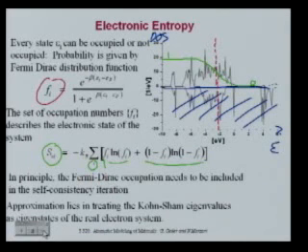So if in an ab initio calculation you calculate the density of states, you actually have a trivial way of getting out the electronic entropy. Okay? And getting the density of states is really rather simple. So you just smear it with the Fermi-Dirac distribution function, and you sum, or you do this as an integral typically rather than summing, and you have the electronic entropy. Okay? It's very simple to do.